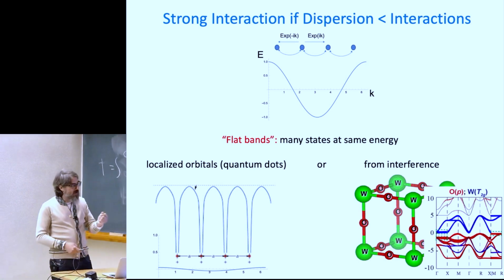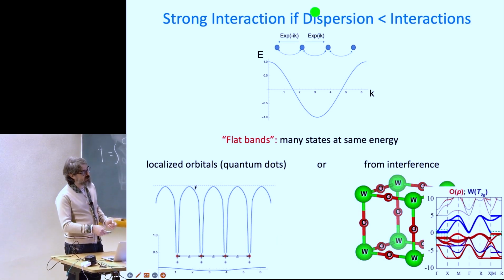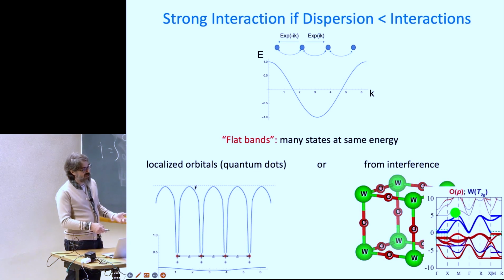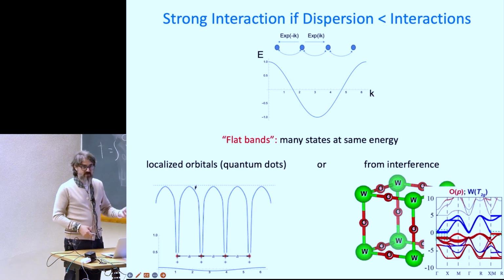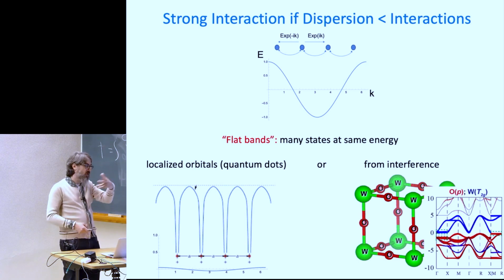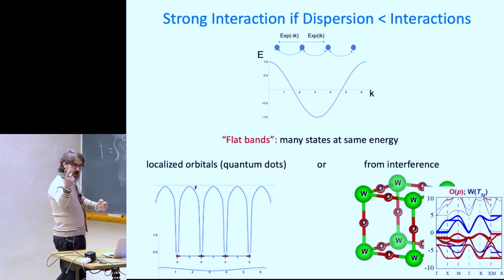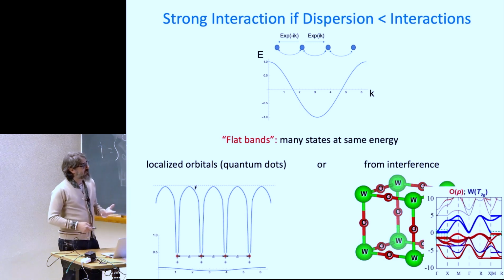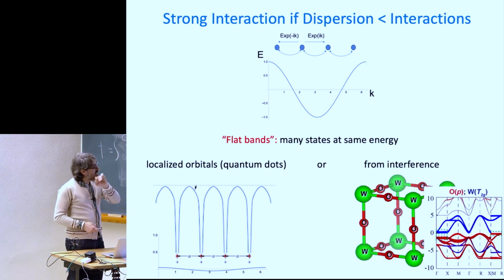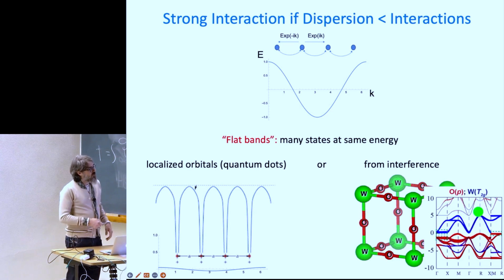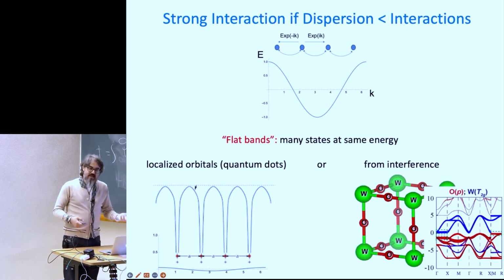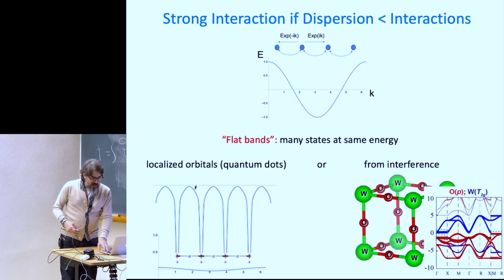The wave function can hop, and you know that it can hop because the amplitude is not 0. How do you know it's not 0? Well, you know that in some directions in momentum space, it has dispersion, so it cannot be 0. But in some other directions, it doesn't have dispersion. So for those directions, there's some cancellation of signs when the electron hops around and comes back, for example. There's some cancellation of signs, even though the hopping amplitude is non-zero, and it's really of the order 3 to 5 electron volts, huge, or more. But for those directions, it's 0 because of quantum interference. And that happens on a Kagome lattice, etc. So that happens in realistic materials.